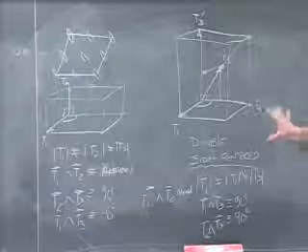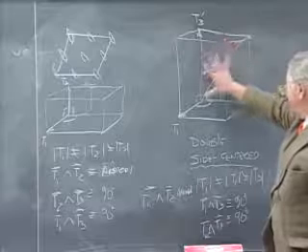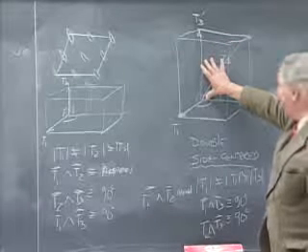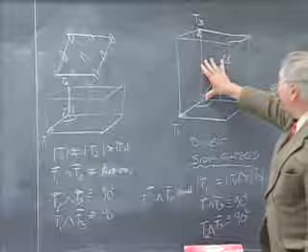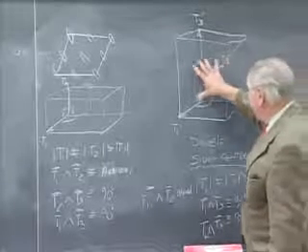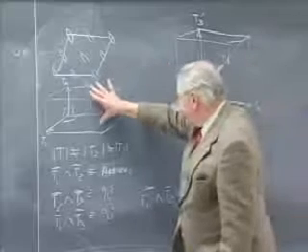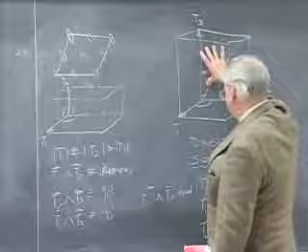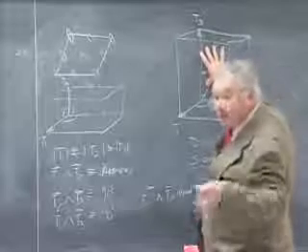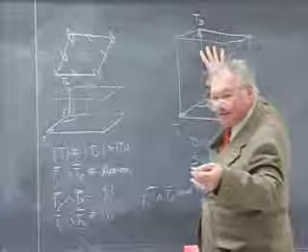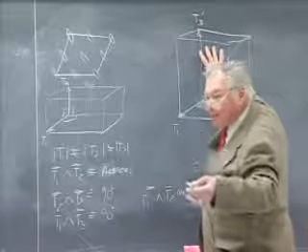Okay, so by picking this double cell, we've defined a cell that has a twofold redundancy. But in doing so, we have gained the advantage of showing that this specialized geometry is exactly the same as this one, in the same sense that in 2 dimensions, the primitive rectangular cell and the centered rectangular cell were both cousins.